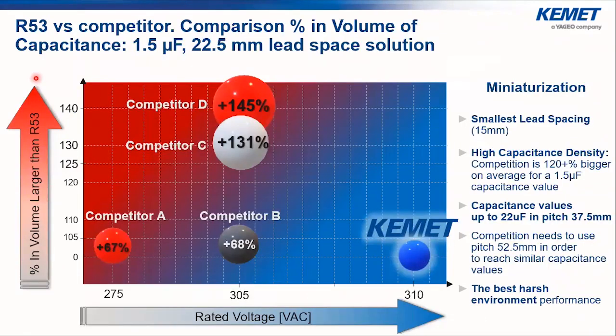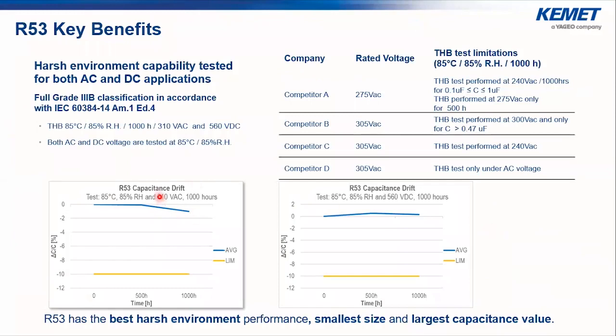If we compare the same volume percentage increase between the R53, that is here our design, with some of our competitors which are present on the market, we can see really a very big advantage. So there are competitors with plus 67, 68%, where the rated voltage is 275, 305, and also other two where we have plus 130, plus 145%. Here also, the biggest advantage is that we can offer 22 microfarad in pitch 37.5. That is the biggest capacitance, and our competition needs to use pitch 52.5 in order to reach a similar capacitance value. So this is a series that has the best harsh environmental performance, and also miniaturized dimensions that really can fit in space limited applications.